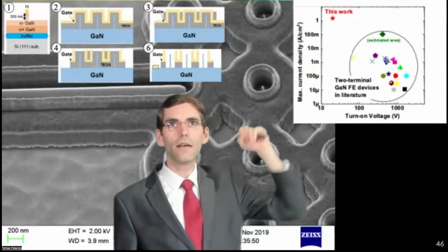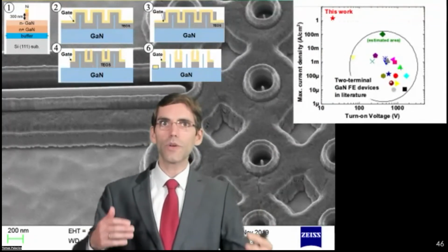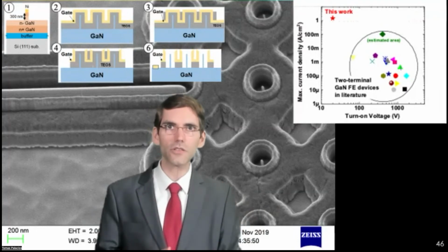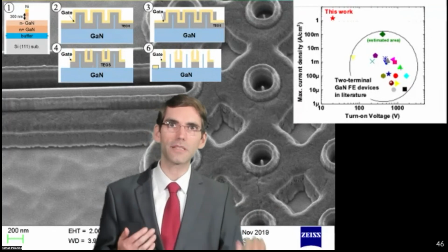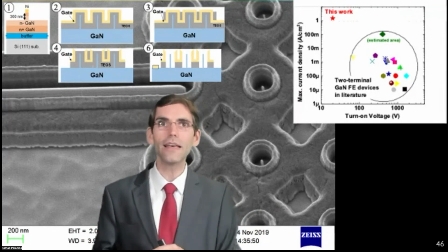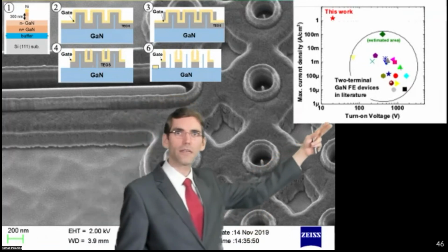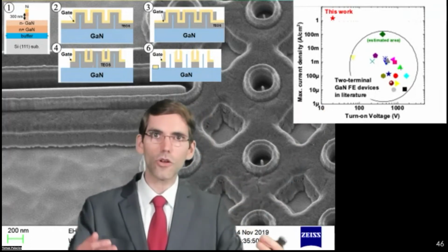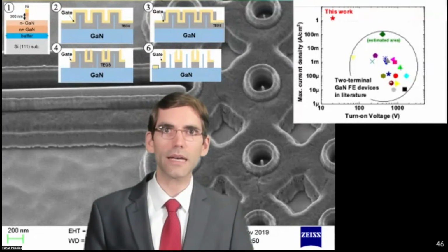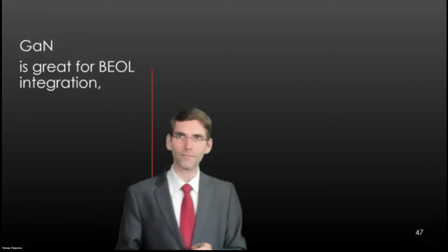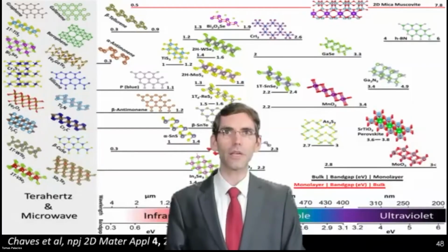This particular device had a maximum current density of around 1 amp per square centimeter. We have devices today based on a second generation structure with between 10 and 100 amps per square centimeter for a turn-on voltage around 20 volts. So we are still working to lower the turn-on voltage for these devices, but we are getting there. I am very excited about gallium nitride. I truly believe it has lots of interesting opportunities, but gallium nitride is only the beginning. There are so many other materials with truly unique properties that we can take advantage of.